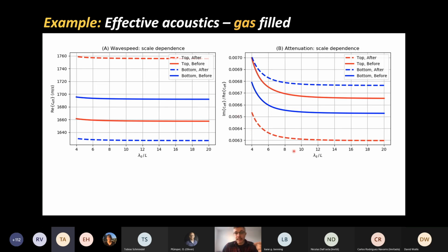But notice, very importantly, that attenuation has a behavior with frequency, and this behavior maintains information about geometry. We know this because if you remember observations about porosity, the top before and the bottom after, these two curves that you see here had similar porosity. But the geometry of the pores, if you remember my description of what we got from those curves, was very different.